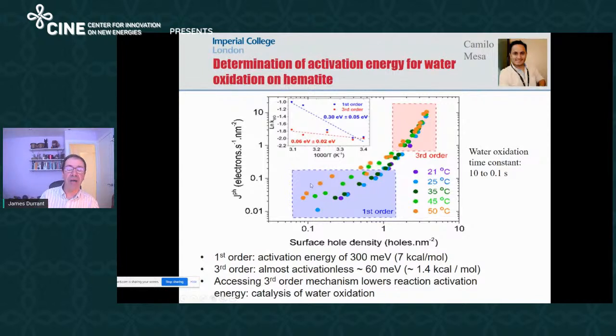And that is probably the activation barrier for holes on hematite, one hole oxidizing OH minus to OH dot. But at high hole densities, we observe the reaction becomes essentially temperature independent. The activation barrier comes down to only 60 millielectron volts. And so that's suggesting that at high hole densities, hematite is able to catalyze the free hole oxidation of water as a third order reaction with a much lower activation barrier. And so in this sense, the hematite is functioning as a true catalyst for water oxidation.